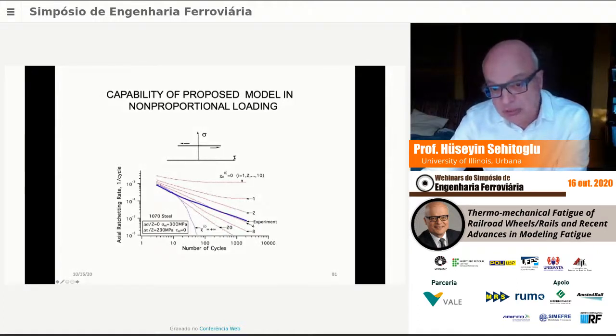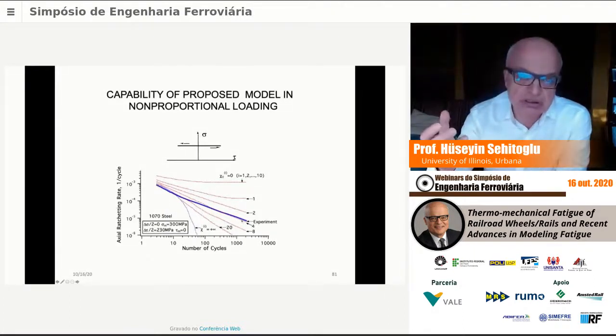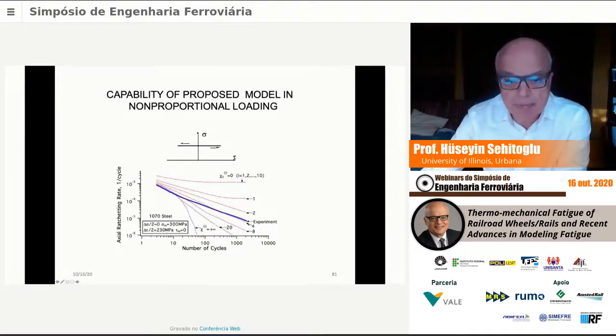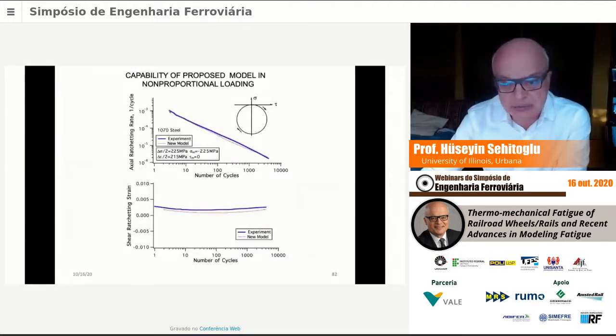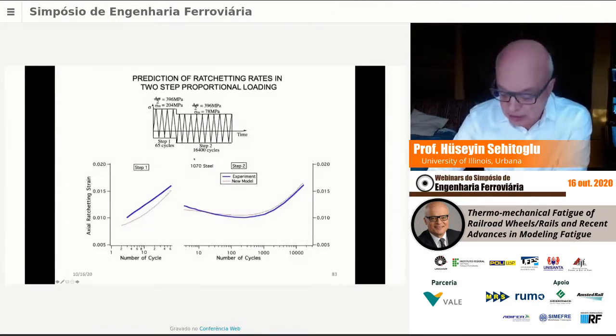This was that experiment where we kept the stress constant, but reversed the shear. These are thin-walled cylinders, tension-torsion experiments, plane stress. We have this capability in our labs. And so the experimental results are here. And then our prediction, with Xi equals 4, again predicts that. And we show again this behavior, the axial ratcheting, even getting some transient shear ratcheting in this case, which we were able to capture.